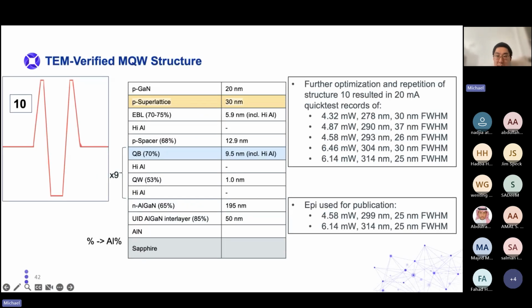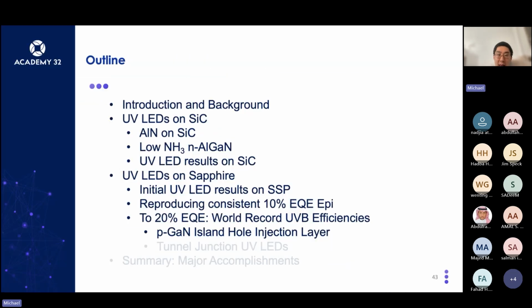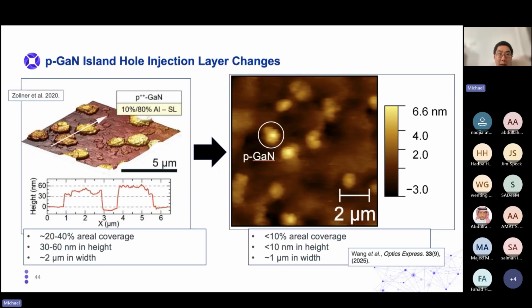So these quick test powers are actually relatively close to the quick test power that I published in 2023 with the 10% EQE. The quick test power that I published in 2023 was about 4.4 milliwatts, just as a comparison. So you'd think that that wouldn't give you this 2x increase in efficiency, because the quick test performance was approximately the same. However, what we discovered was that with this thinner n-type aluminum gallium nitride material, our stress state at the top of the LED is different.